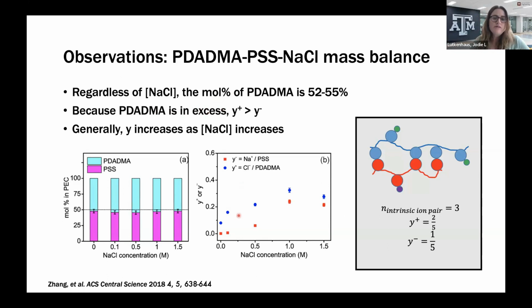Then we have the doping levels that we can measure. As we increase the salt concentration of assembly, the doping level increases as well. This is showing the effects of screening. The salt is breaking up intrinsic ion pairs up to a point. At 1 molar, we could say about 30% of the PDADMA is unpaired, or 30% of the PDADMA is paired with a chloride ion instead of a polyanion. That's an example.